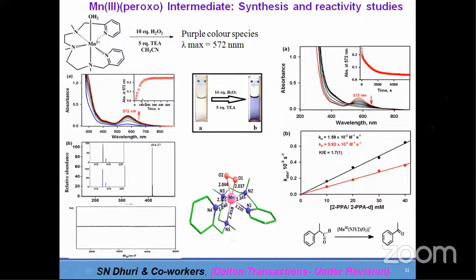And you can see these are the spectra on addition of the hydrogen peroxide. So it was quite stable. The species is also characterized by ESI mass, EPR, etc. Then we also got some DFT calculations done by my colleague from Central University of Haryana. He showed that, for the solution we have and the manganese peroxide species we propose, DFT shows that it is a side-on species.